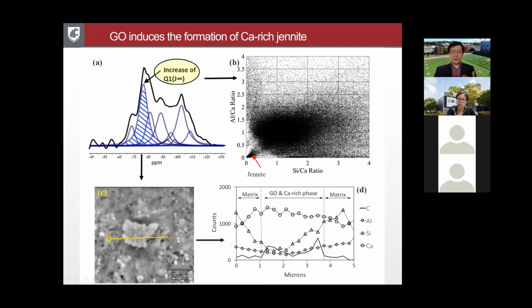So in other words, pervious concrete is a very green design for concrete pavement, but can it get even greener by replacing that cement with a greener binder? So that's our motivation here. So we developed 4 different groups. You can see cement and cement plus the trace amount of graphene oxide, or fly ash, which is actually activated fly ash, and fly ash plus graphene oxide. You'll notice there's a slight increase in the second 2 groups in terms of water binder ratio because we had to achieve comparable workability.